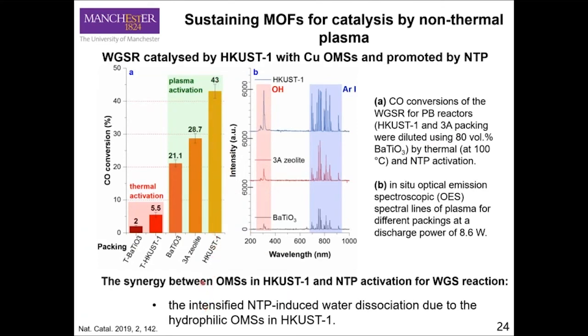Okay, and compare with this kind. This is the pure plasma system with the inner packing, and this is the HKUST-1 catalyst. Also, as a control experiment to show the porous materials can enhance the plasma activation. Here is the thermal case. Compared to the one under plasma condition, it's not comparable at all. And we also did some in situ study to understand what exactly happened.